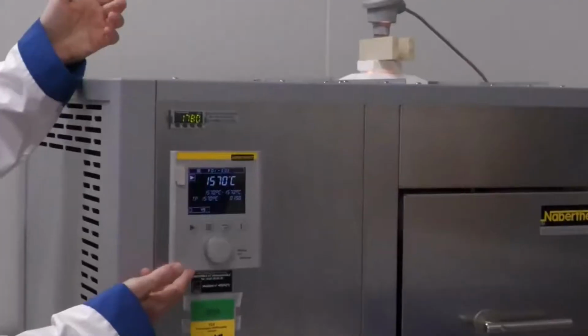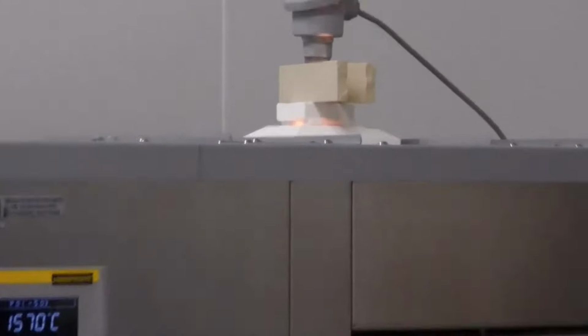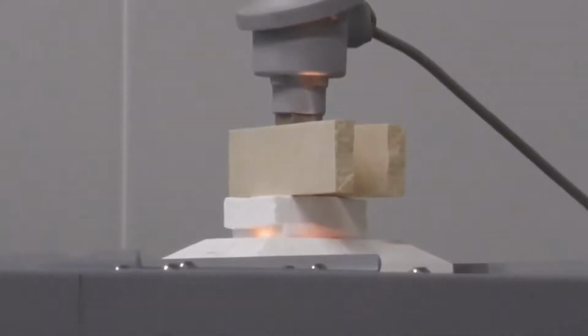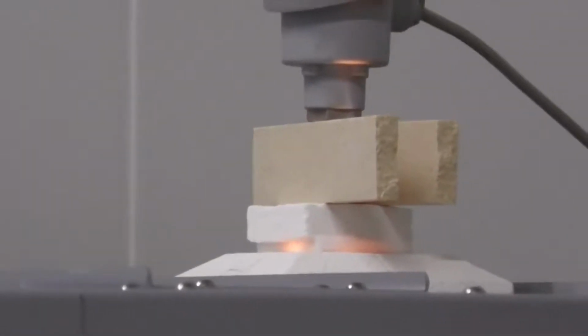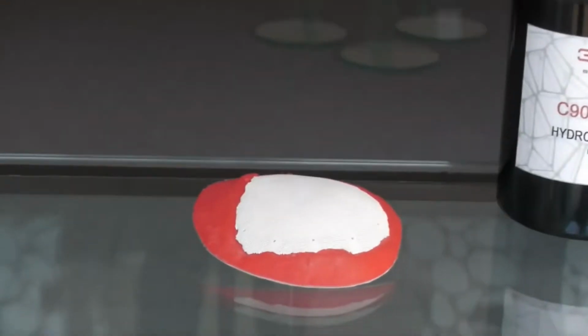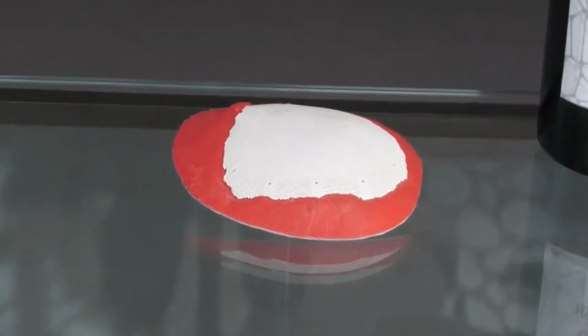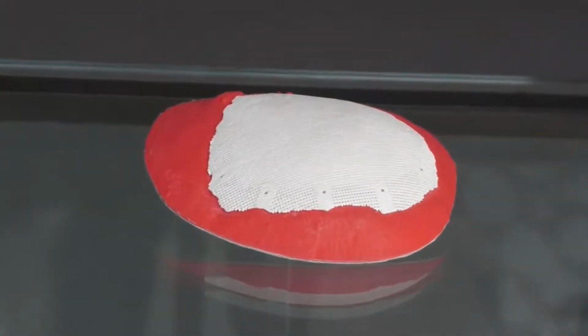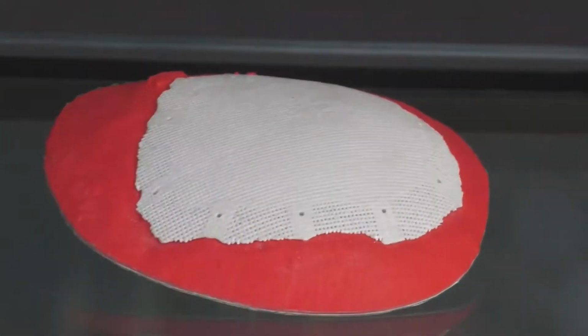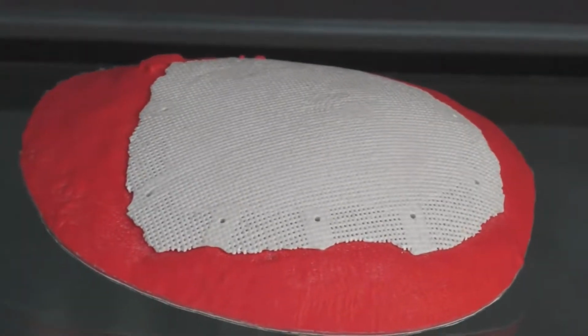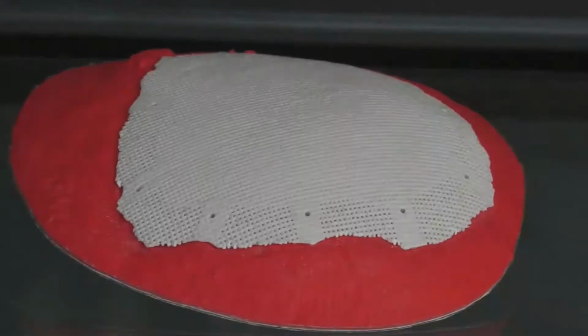The debinded parts undergo a new thermal treatment in another category of furnaces that can reach very high temperatures, over 1000 degrees C. The porous ceramic structure obtained after debinding will become dense and the object will undergo a strong shrinkage to reach its final dimension, 10 to 25% of the green part. The small ceramic grains, until then only in contact, will bind very strongly and grow until you obtain the porosity and the mechanical properties you are looking for.